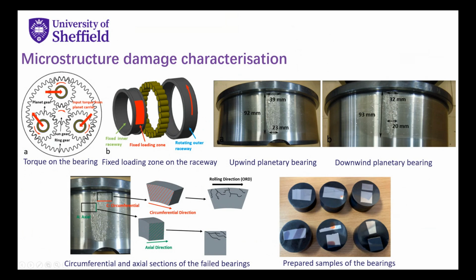In the real bearing, you can see a certain area on the surface is damaged, but not everywhere—it's fixed to a certain area. I'm going to look at the subsurface damage in the circumferential direction and axial direction to see the difference between these two sections. Before we use the optical microscope and SEM for observation, these samples should be polished and etched, as shown in the picture.